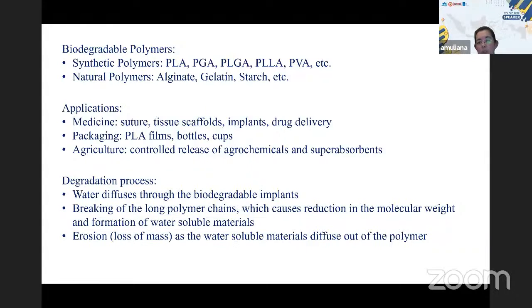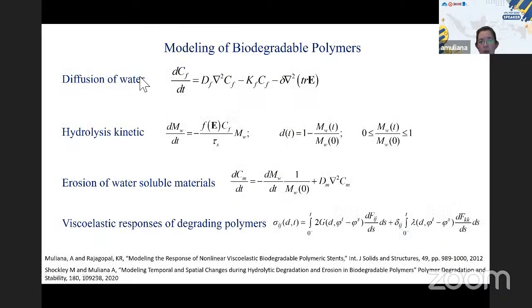So now, how do we approach this problem? What we did, okay, is we need all these basic components. Start with the diffusion of water. So CF is the water concentration, right? And we also have this component for the water consumption during the hydrolysis process. And some studies suggest that when you strain them and there is mechanical loading, it also alters the diffusion process. Then you can also include that component here, right? Now during hydrolysis, as the polymer chain breaks into smaller and smaller chains, it's quantified through the molecular weight change. So the molecular weight decreases as the hydrolysis process continues. While this decrease in molecular weight is, in our case, how we look at the degradation.